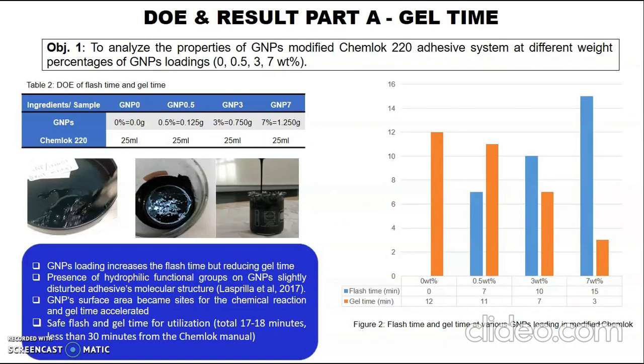Next part is to achieve objective 1, the gel time test study. This is a DOE of flash time and gel time, and this is the result. The result shows that GNP loading increased the flash time and decreased the gel time. This is due to the presence of hydrophilic substance on GNP that disturbs the adhesive structure.